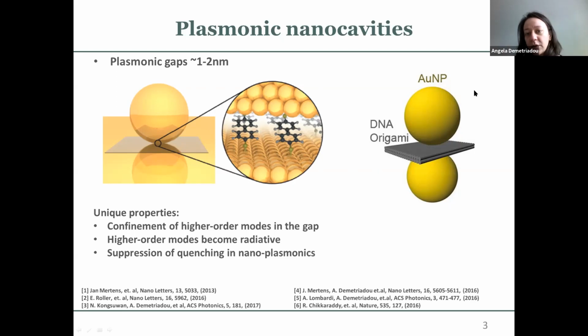There are other groups that use other techniques like DNA origami, which gives you even greater control on the size of the gap. However, it's more difficult to go down to 1 or 2 nanometers. It's usually around 4 or 5 nanometers with the DNA origami. Why would anyone need such extreme gaps? Why would you need such small plasmonic cavities?